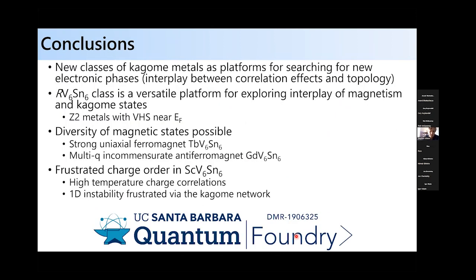Okay, so just to conclude, in general, I think we're all here because we think kagome metals are interesting platforms for looking for new electronic states due to their interplay between correlation effects and non-trivial topology. The 166 class, of course, is very versatile. We think the vanadium-based class is an interesting one because you can tune a non-magnetic kagome net relative to a triangular lattice of rare earth ions. Our initial work shows that you can realize a diversity of magnetic states. And the scandium 166 compound is a unique member of this class of compounds because it realizes what seems to be a frustrated charge order at high temperature. And with that, I'll thank you very much for your attention.